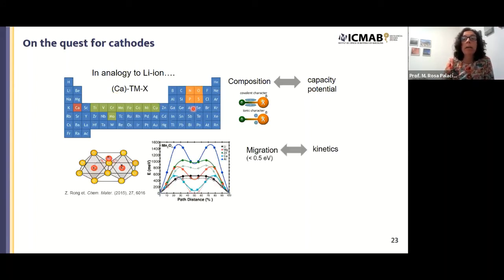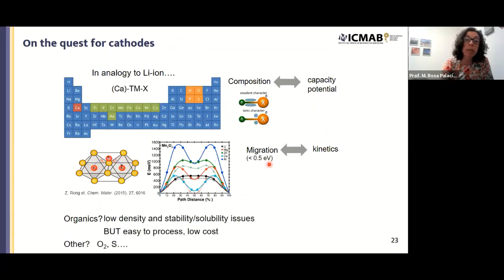Another relevant thing is that the compound used as cathode has to enable migration of calcium within the crystal structure with good kinetics, which means migration barriers lower than 0.5 electron volts, or at least lower than 0.7, which is not trivial. Other cathodes one could think of are organics, and some people are starting to work with them. The main issues would be the same as when applying organic materials in lithium-ion technology: stability, low density, or solubility in the electrolyte, but they have the advantage that they are easy to process and low cost. And of course, one could think of more exotic concepts like calcium-oxygen or calcium-sulfur. But these are concepts which are not yet solved with lithium metal as anode, so also tricky ones.